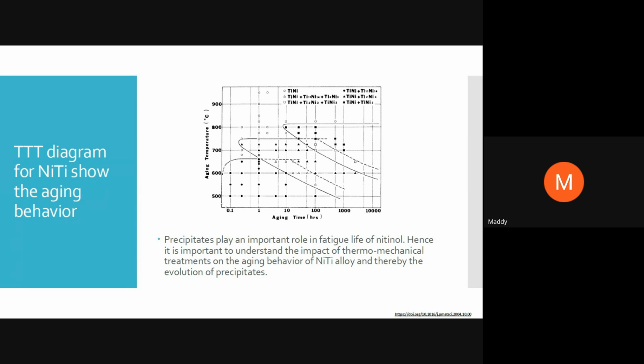But I would say that one should aim for Ni4Ti3, a nickel-rich precipitate, which is approximately a few nanometers in size. And it should be in a position where it is able to exert some stress in the matrix and strengthen the matrix. I would leave it at that. So that's what you learn from these diagrams. It's important that for the specific alloy you're looking at, you're familiar with this. Next slide, please.